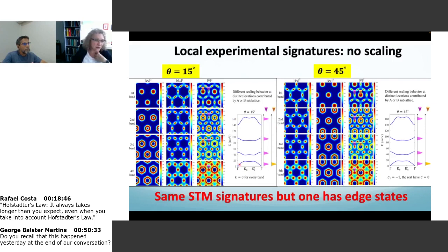But it will have contribution of all the other states that are above the 0 mode, that have slightly higher energy, all these states that disperse in this part here. And they will contribute there. But since these states belong to the linear part of the Dirac spectrum, that when I apply the superlattice gets folded, what I am seeing really is these bands that are folded, and the folding appears with a scaling that depends on the superlattice period. So the separation between these bands will depend on the superlattice period, and they will give me